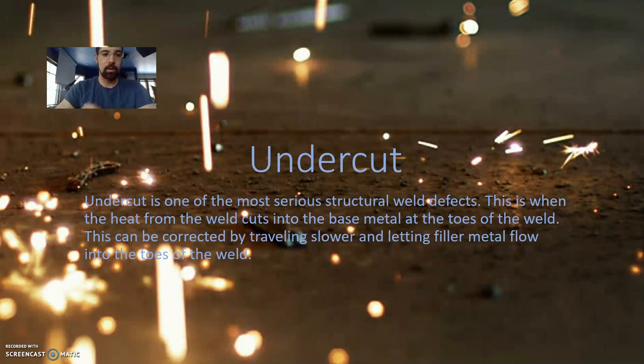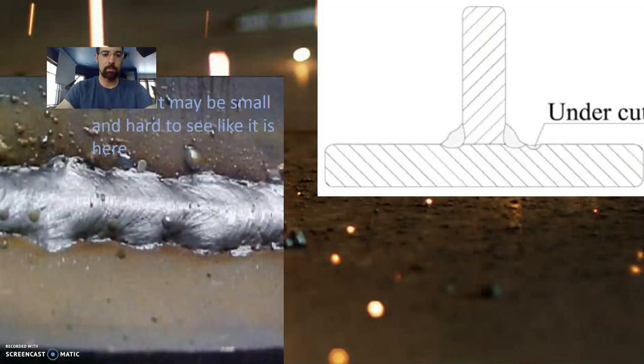Undercut. This is one of the most common and also one of the most serious weld defects out there. This is when the heat from your weld cuts into the metal at the toes of the weld, the edges of the weld. It compromises the structural integrity of your weld, of the metal. And if you have it in a weld test, you will not pass.